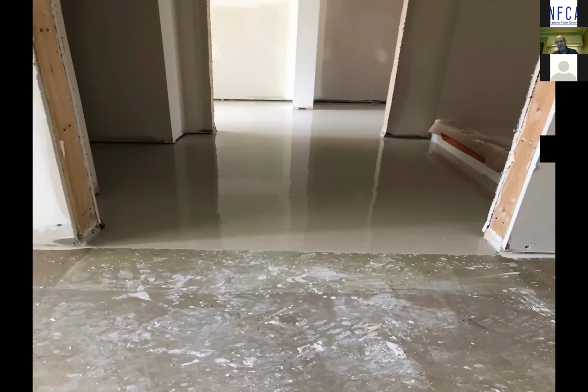So if you have to self-level a gypsum floor, in theory, you should use a gypsum product on top. And this gives you your best equilibrium. Like I mentioned earlier, gypsum doesn't shrink. So using a gypsum product on top of a gypsum product, you still have to have a strong enough substrate to stick it to, and you still have to have it primed properly. But at least a gypsum material is not going to put an undue amount of shrinkage and pull on a substrate.